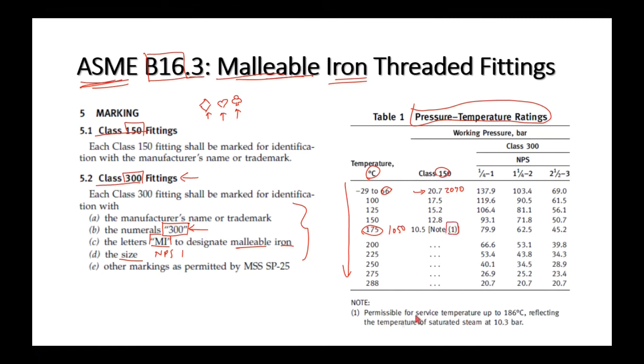And there's a note there too. Permissible for service up to 186 degrees Celsius, reflecting the temperature of saturated steam at 10.3 bar. So really, you can't use this over 1030 kPa. And as a matter of fact, you're really stretching things then. Now, as for class 300 fitting, let's say it's NPS quarter to 1. That's the range of sizes. Well, this one here is good for 13,790 kPa at 66 degrees. At 175 degrees it's good for 7990 kPa. You get the idea. Now, what they have in common is every time there's an increase in temperature, we see a reduction in the allowable working pressure.